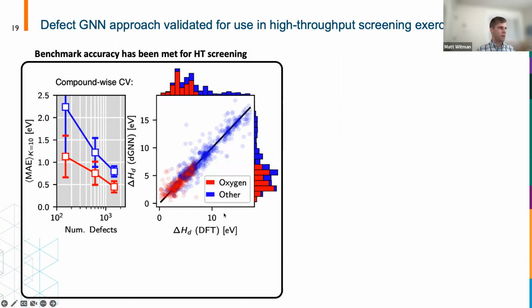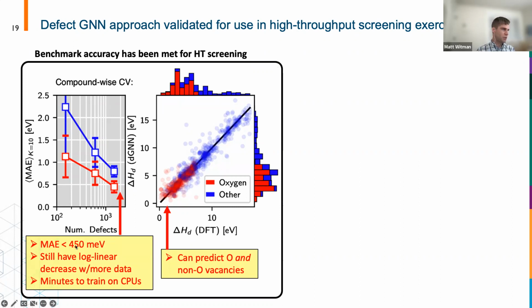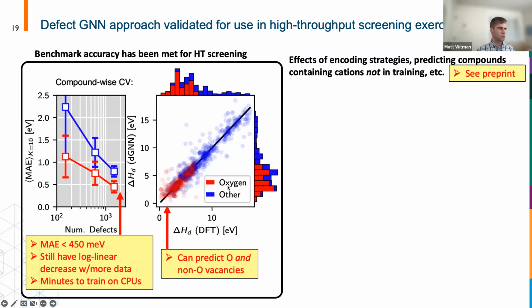And here I'm showing the parity plot for all the test set predictions across all the K-folds in our cross validation. And you can see, this is the exact same model that's predicting oxygen and cation vacancies, same exact model, same exact weights. So that's what we mean by this approach being generalizable, and it's really only going to be limited by the amount of data that you give it. So again, we can get to a sufficient oxygen error that we can do this for materials discovery, and this is super fast to train and execute. And then we can predict the vacancy of any crystal site in the structure.